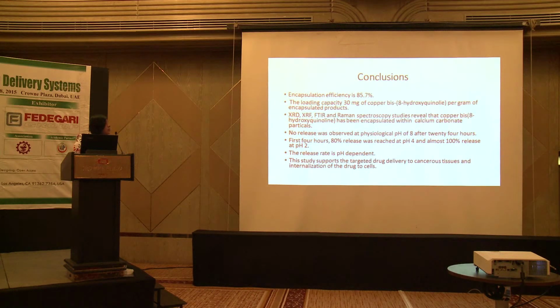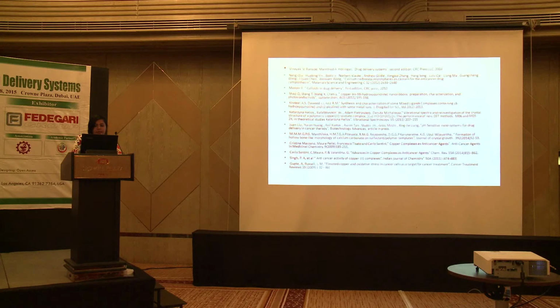No release was observed at physiological pH of 8 after 24 hours. In the first 4 hours, 80% release was reached at pH 4 and almost 100% release at pH 2. The release rate is pH dependent. This study supports targeted drug delivery to cancerous tissues and internalization of the drug into the cells.